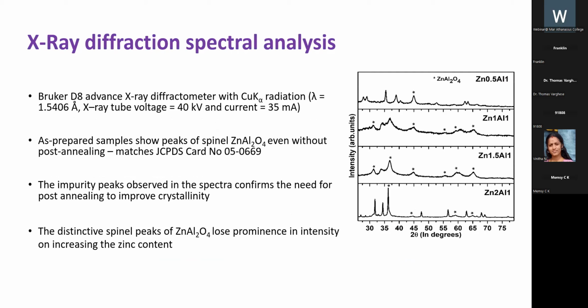And now moving on to the results. First, I have done the XRD analysis in order to check if the structure is formed or not. The equipment used for the XRD analysis is a Bruker D8 Advanced X-ray diffractometer. The as-prepared samples show peaks corresponding to the spinel zinc aluminate, even without post annealing, but it is not perfect. So in order to make it a completely spinel structure, we have to do firing, that is calcination. Also, the distinctive spinel peaks corresponding to zinc aluminate lose their intensity on increasing the zinc content.